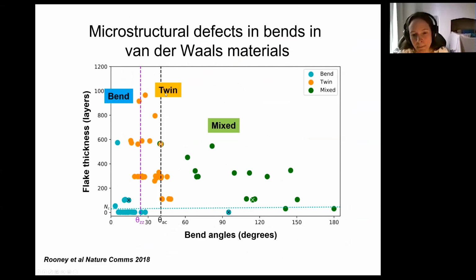Now, we can then do the same thing experimentally. We can see the same type of behavior as that theoretical phase diagram. So again, thin flakes will bend, and at very small angles the flakes will bend. In this intermediate region, thicker flakes at small angles, we get this twinning microstructure, whereas at large bend angles and slightly thicker flakes, we get these more complicated mixed microstructures.